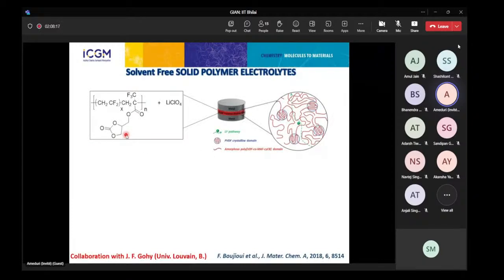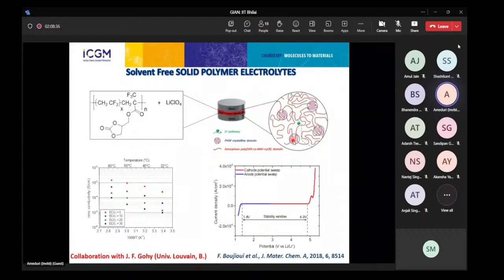So when we look at my colleague Jean-François Gohy, professor at the University of Louvain in Belgium, he used lithium perchlorate in the system and showed that you have a different structure. Of course, it's a semi-crystalline polymer because of the presence of PVDF units, but it's also elastomeric. And when you look at the conductivity versus the temperature, this is 80 Celsius, okay?